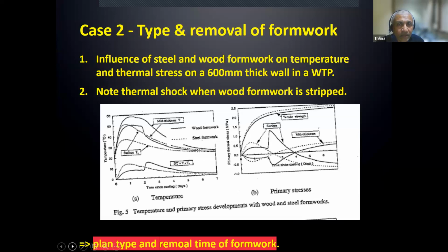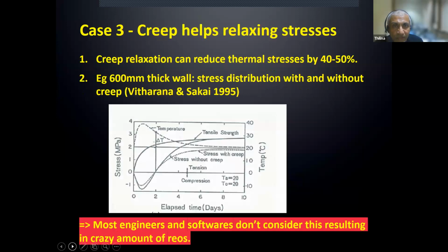Case 2, type and removal of formwork. People think removal of formwork is only to get strength. No, you get some members' thermal shock as well. Steel formwork allows heat to be lost because the conductivity of steel is much higher. When you remove the steel formwork, there's no thermal shock. But if you use wood formwork and suddenly remove it, you get a thermal shock. You can see the change in stresses on the one on the right, my right hand side. So formwork removal and type of formwork need a little bit of thinking, rather than just saying formwork removal is to do with the concrete getting the strength. Next one, please.